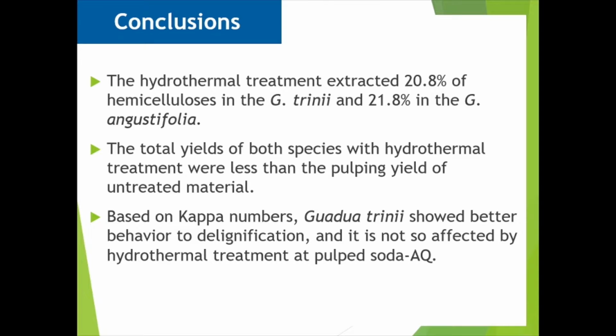The hydrothermal treatment extracted 20.8% of hemicellulose in Guadua trinii and 21.8% in Guadua angustifolia. The total pulping yields of both species of material with hydrothermal treatment were lower than the total yield of untreated material. Based on kappa numbers, Guadua trinii showed better behavior to delignification, and it is not so affected by hydrothermal treatment, as in the soda and anthraquinone pulps.